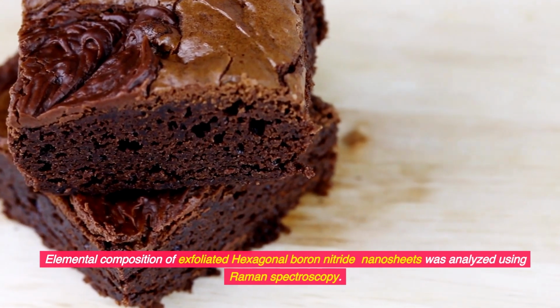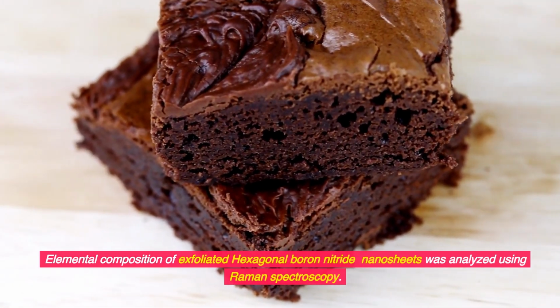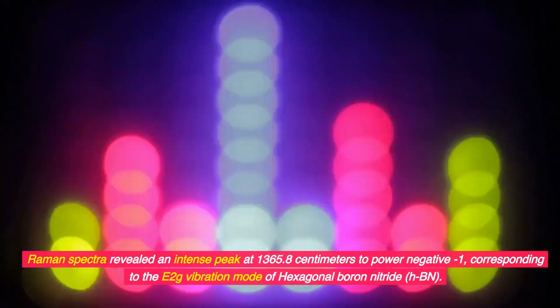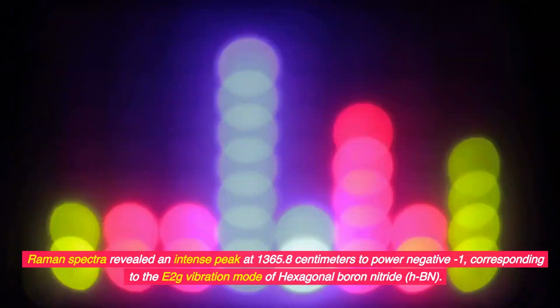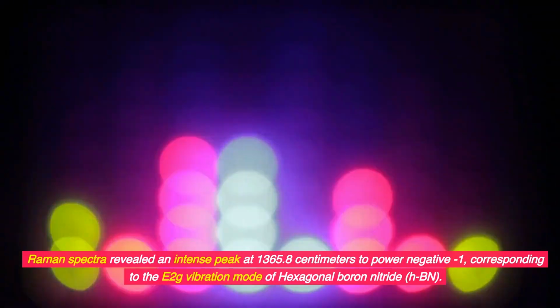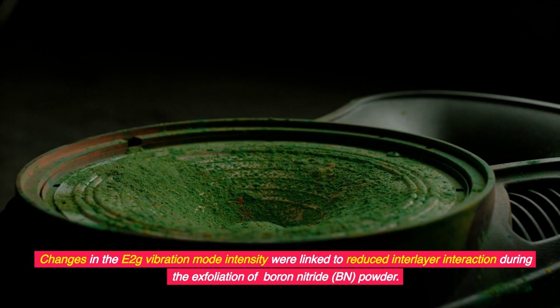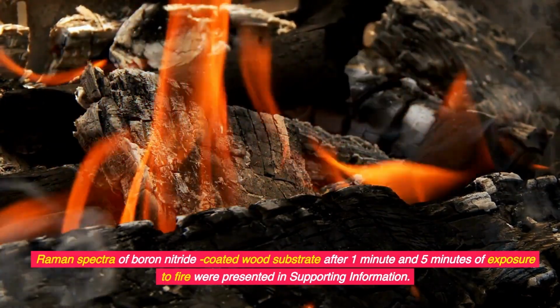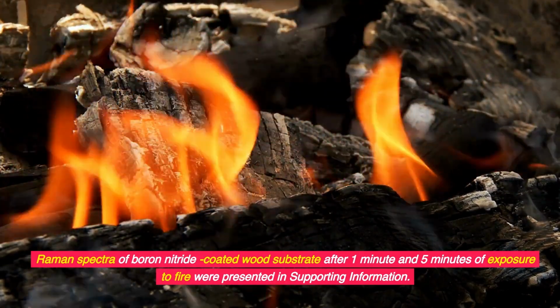Elemental composition of exfoliated hexagonal boron nitride nanosheets was analyzed using Raman spectroscopy. Raman spectra revealed an intense peak at 1365.8 centimeters to the power negative 1, corresponding to the E2g vibration mode of hexagonal boron nitride, HBN. The FWHM of this mode was 5.21 cm^-1, indicating high-quality hexagonal boron nitride HBN nanosheets. Changes in the E2g vibration mode intensity were linked to reduced interlayer interaction during the exfoliation of boron nitride BN powder. Raman spectra of boron nitride coated wood substrate after 1 minute and 5 minutes of exposure to fire were presented in supporting information.